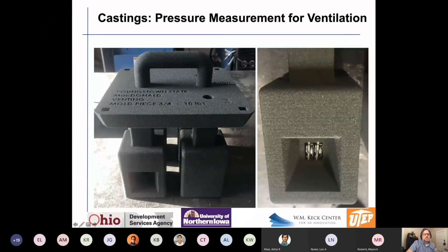So here's some 3D printed sand. This is an experiment I did like 2 weeks ago. And what's happening here is this thing fits down into a cavity also, and it fills up. And these, there's 4 of them, are cores that hang down from the ceiling. And as the metal fills in, this sand, which is 3D printed, starts to decompose and it builds up pressure. And that's a real problem. And so we're measuring the pressure with these 2 sensors for redundancy. And we're hoping to actually cause, in some cases, bubbles to pop out into the metal and cause problems.